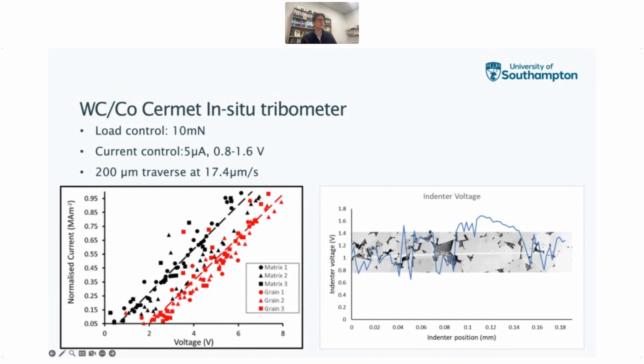And you do start to get discrimination between the voltages and therefore the resistances that are coming out between the two phases. But you have to start taking account of the area that your tip is actually encountering then, and that's a little bit challenging because you've gone from a nominally controlled indent, perhaps, to something where you're laterally traversing, and what that means is that the response of the material determines the contact area, and that's a little bit difficult also to determine what that actually is. So that's the next challenge, really.